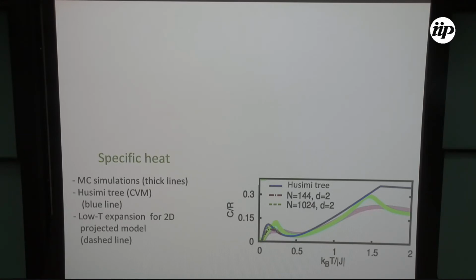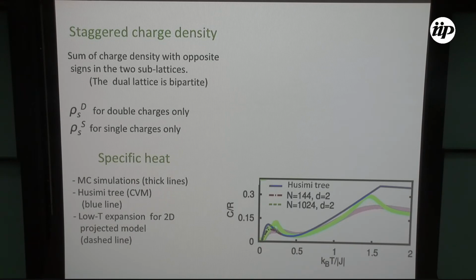So the way in which you can understand these features is by looking now not simply at the charge density, but at the staggered charge density. So what I'm calculating is the density, like in an antiferromagnet. The staggered charge density means that, you remember I said that this diamond lattice is bipartite, so I can define the 2 sublattices. Now I'm going to calculate the density in one sublattice and the density in the other. And rho S is going to be non-zero if I have opposite charges in the 2 sublattices, right? So I can calculate this for single charges and for double charges.